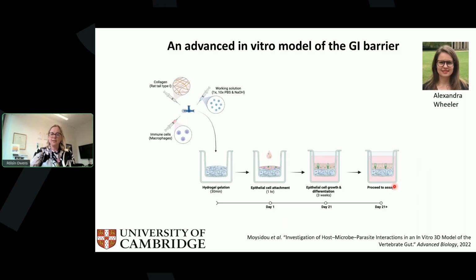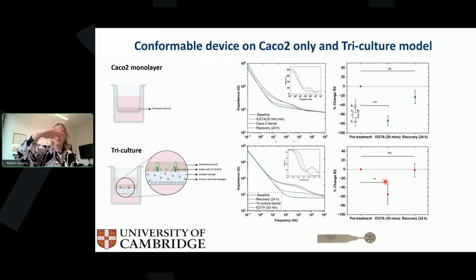We have differentiated tissues, and we've checked that using standard electrodes. One thing to point out, though, is that these gels sometimes contract, which makes a standard electrical resistance measurement with an electrode above and below very difficult, because all of the ion flow goes on the sides where the tissue is pulled away. That's not a problem with our device because it sits on top of the tissue. We had previously shown we could do this with monolayers. We place the device on top, you see the baseline, you add the cells, and you see the shift, and then you can extract the resistance.